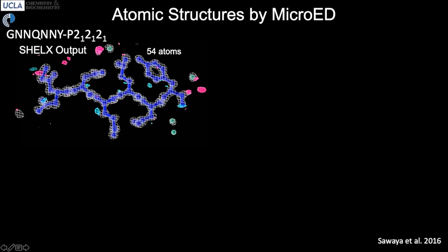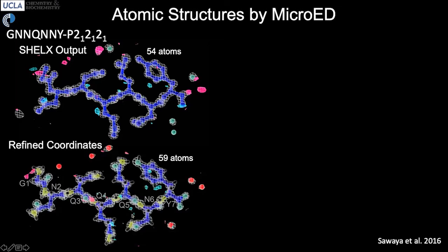In this case, you can see an example of such an assembly of atoms that was identified by the SHELX program. For anyone who's looked at peptides before, this very much looks like a canonical peptide. It's actually a heptapeptide structure. You can place atoms at these locations and then optimize or refine those coordinates to obtain a more or less final structure. Out of that final structure, almost all of the atoms, 54 out of 59, were identified by the ab initio phasing program. The remaining atoms were identified during refinement as locations in space where density was present, but an atom wasn't placed by the program. So this was done manually.